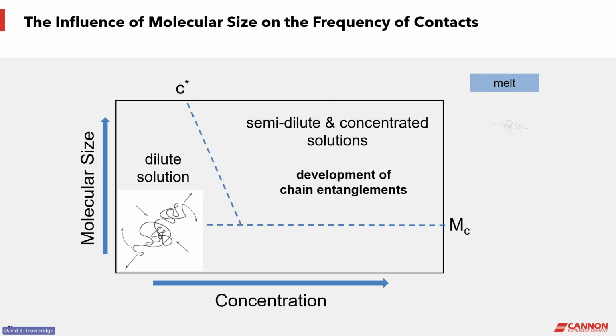At the other extreme, where there is no solvent, we would like to think about this state, but it really is not the state we're in. There's no solvent. The molecule is not swollen by the action of the solvent working to expand the polymer. And more significantly even, there are other polymer molecules in the very same vicinity forming entanglements. And I went to the effort to show these pictures on the graph, because some practitioners measure the melt flow, the viscosity of the melt flow, and try to relate it to the intrinsic viscosity. But you can see the state is very different.